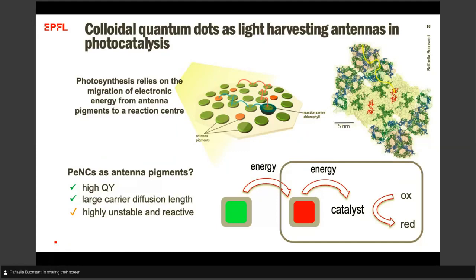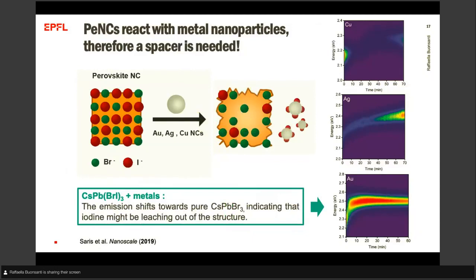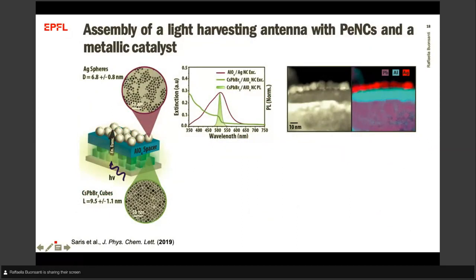Now, I must say that we also discovered that this spacer is absolutely needed, because if you mix these perovskite nanocrystals with the metal nanoparticles, they will react with them. Basically the iodine will be driven out of the lattice, and this will cause chemical changes, and of course changes of the optical properties. So having this spacer of alumina is extremely needed. My PhD student built this light harvesting antenna, which included a layer of perovskite nanocrystals, the alumina spacer, and the silver nanoparticles on top.